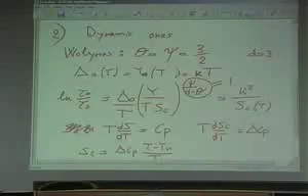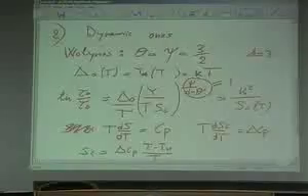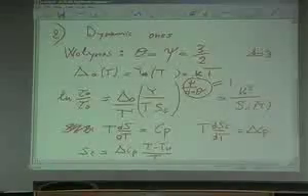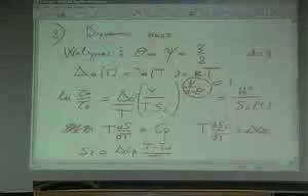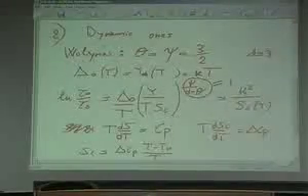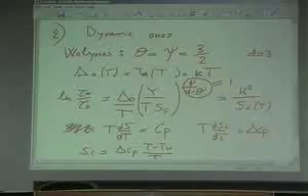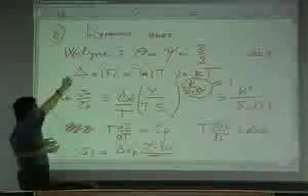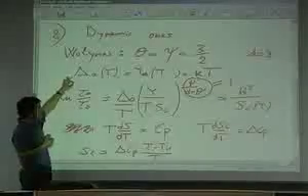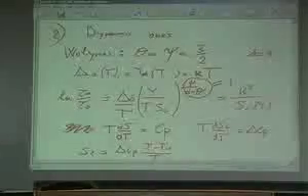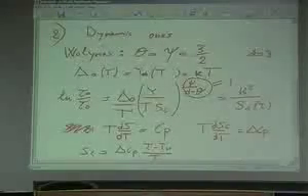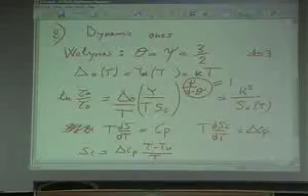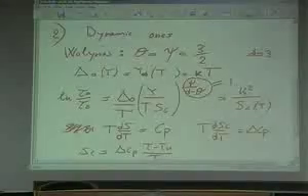I think what Wolynes has said is that liquids in this regime are very well approximated by hard spheres plus a small correction. And if you have hard spheres plus a small correction, what gives you this is entropy. So when you decrease the temperature, this is going to decrease, and then probably it will reach a constant value when you go to very low temperature. But again, it's not that I'm unconvinced; I'm just telling you what he said.